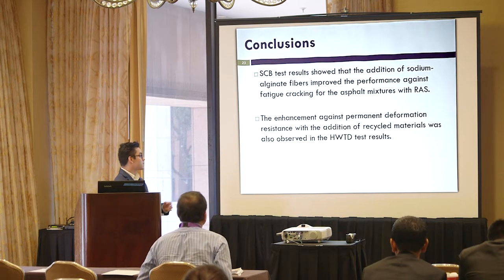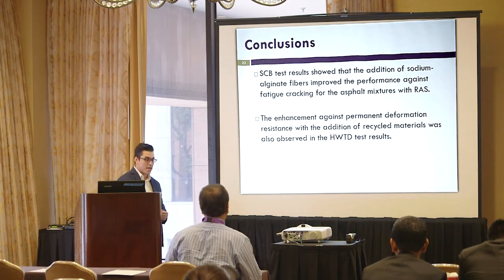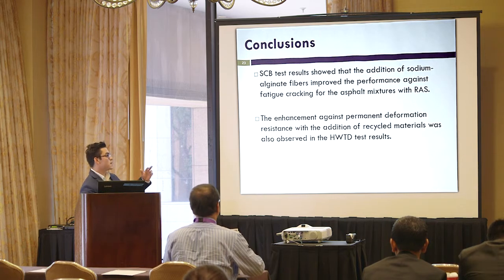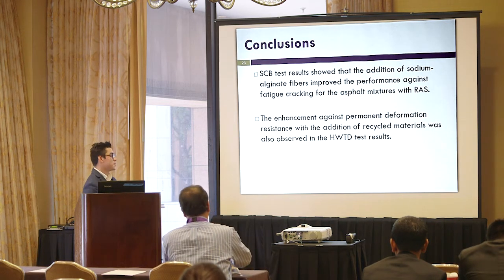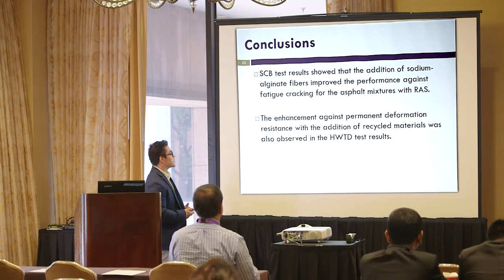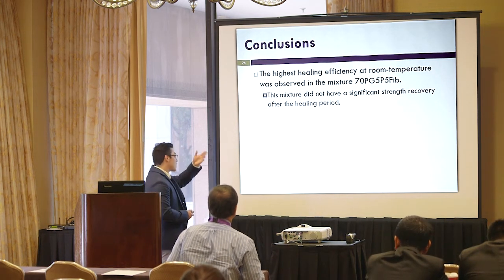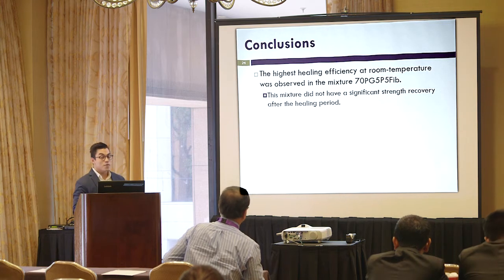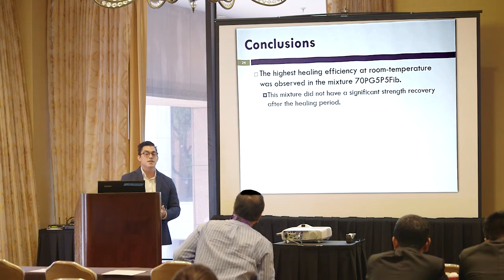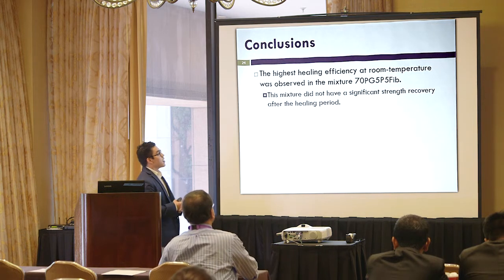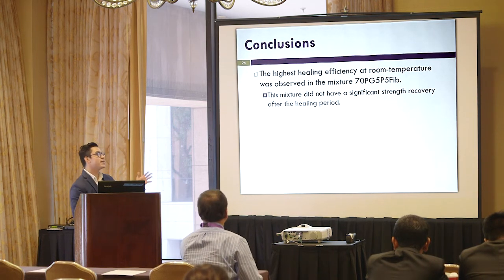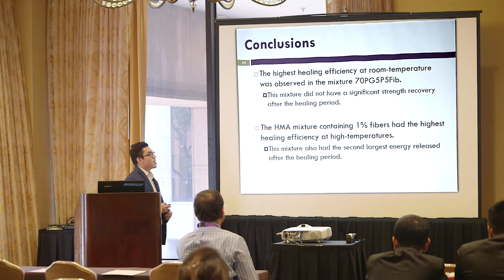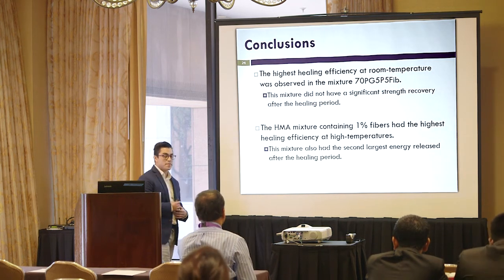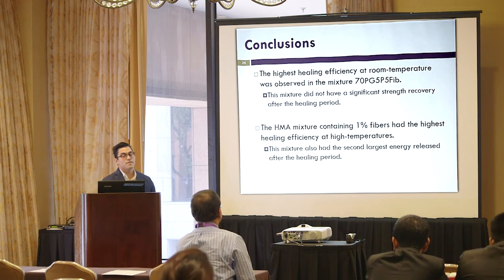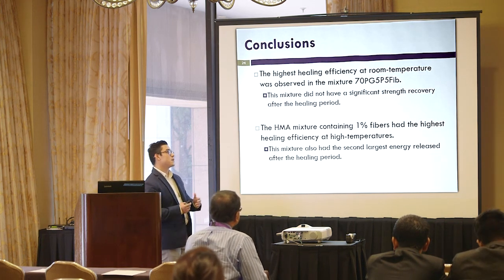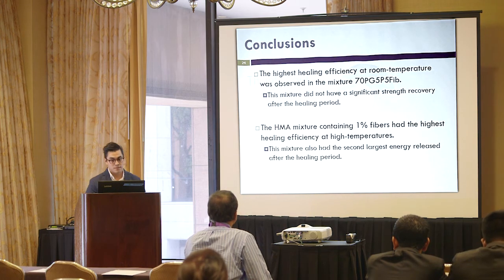And for the Hamburg wheel tracking device test, we observed the same behavior as the MSCR test results, where adding recycled materials and the fibers improves the performance against permanent deformation. For the self-healing test, we observed that at room temperature, the mixture containing 5% RAS and 5% fibers got the highest healing efficiency. However, it didn't have a significant strength recovery. And for the high temperature environment, the mixture containing 5% RAS and 1% fibers had the highest healing efficiency. Thank you.